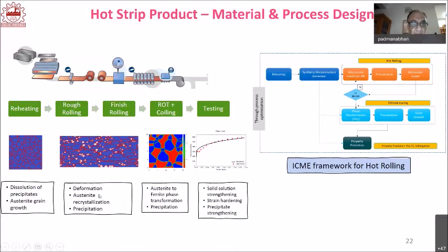And austenite recrystallization, to what degree it happens, and then precipitates will be there, because if you have titanium and vanadium, naturally carbides will form. And in runout table and coiling, austenite to ferrite transformation is there, and also precipitation is there because the solubility decreases as a function of decrease in temperature. And finally, you have to predict the properties by virtual tensile experiments. And here you have to take solid solution strengthening, strain hardening, and precipitation strengthening. Of course, normally you add it, and therefore you use an additive law. There is no guarantee that it should be additive law, but this is the simplest thing. And if it is not working, you go for higher degrees and adjust it and so on. So property prediction also completely becomes possible.